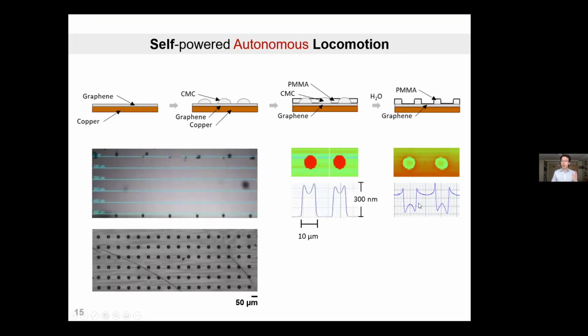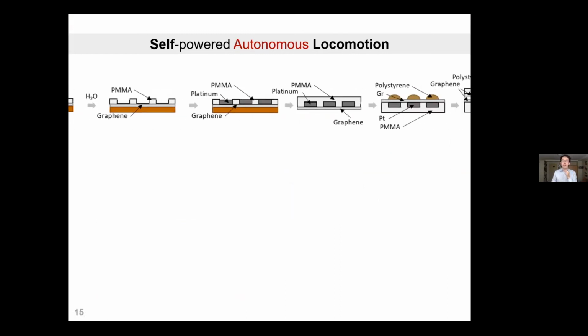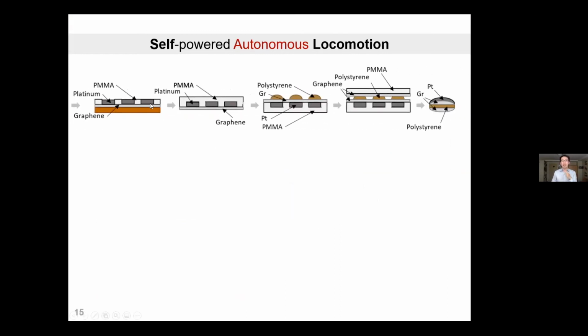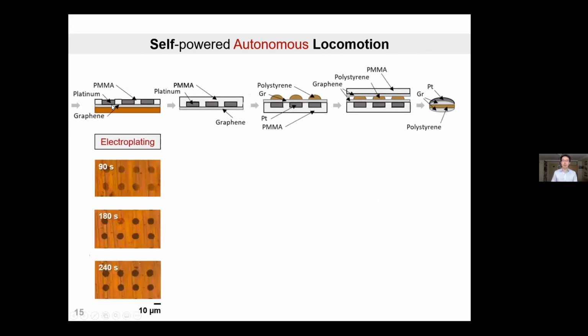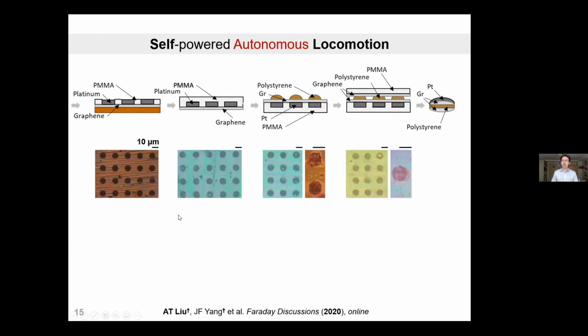that you see here. So what this microwell allows us to do then is to create a fabrication methodology where we can use electroplating to electroplate different kinds of metals on top within the microwell, because graphene, for example, is conductive. So we can use electroplating to do this. As you can see, the platinum that we chose to electroplate within the microwell appears to be this dark color. So if you follow through the fabrication, add this step onto our original autoperforation fabrication, you can basically make particles that, after the autoperforation process, will give rise to this Janus platinum layer on top of the